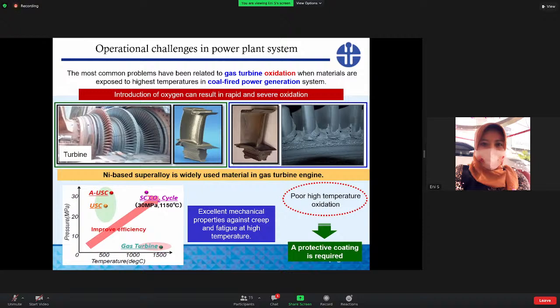The problems are related to gas turbine oxidation when the material is exposed to high temperatures in coal-fired power generation systems. This figure shows the scale observed when operating at higher oxidation. It is known that nickel-based superalloys are among the primary materials used as components for a gas turbine engine, especially for turbine blades, because of their excellent properties against creep and fatigue at high temperatures. However, nickel-based superalloy has poor high-temperature oxidation resistance. Therefore, a protective coating is required.